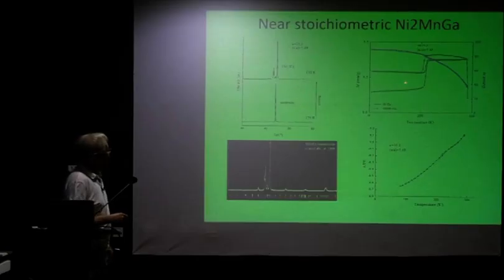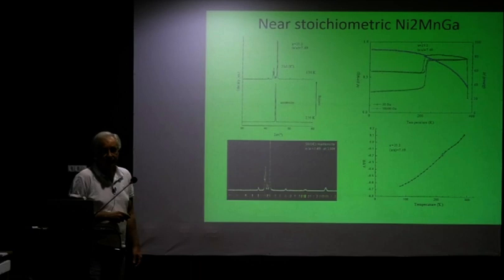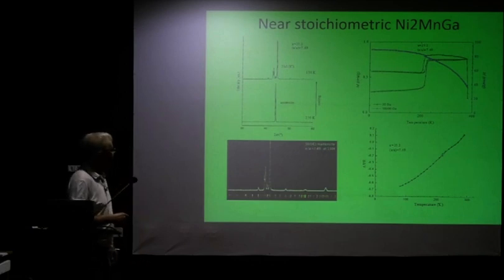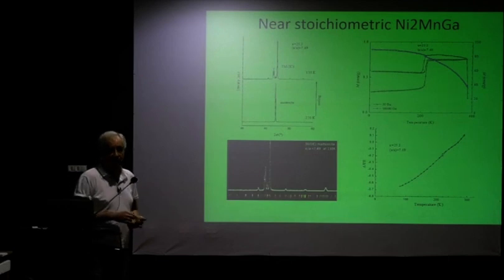So and then you have your magnetization. What does this tell you? 130 Kelvin is somewhere here, and that looks like a pure Martensite state. There is no hysteresis down here. And then you look at your resistivity. Your resistivity shows around 200 Kelvin, which is around here, also a small hysteresis, which is associated with the Martensitic transition here. Okay. So now you have here a transition from the austenite to a 5M Martensite, and it seems that nothing much else is happening at the lower temperatures.